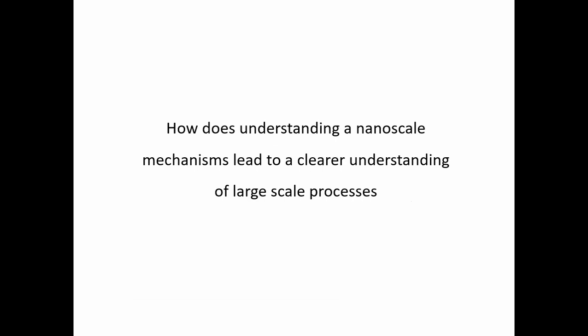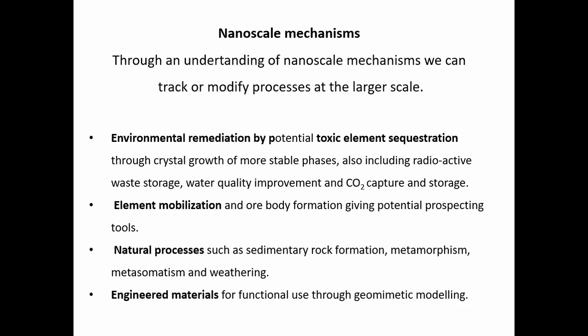Yeah. So how does an understanding at the nanoscale lead to a clearer understanding of larger scale processes? So I've written here that these are all of the issues that we can try to understand by knowing the mechanism of what's happening at the mineral fluid interface. Environmental remediation, as you've seen from all those toxic elements that I was able to show, ended up in the new phase. If we had a barrier of calcium carbonate across streams or whatever that were contaminated, we could sequester the toxic elements in a new phase, and this would happen actually quite quickly in terms of days. What I'm doing is in terms of minutes.